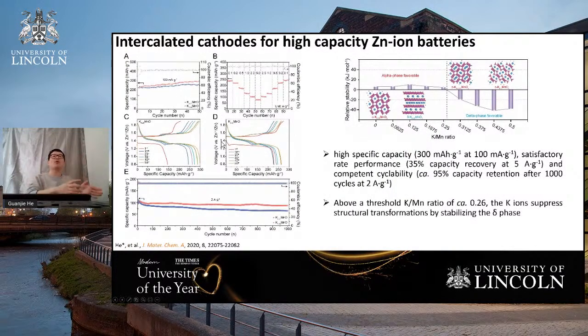Due to more potassium ions, they may occupy more host structures for the zinc ions, but our results show a controversial result. We showed that potassium 0.28, the higher amount, shows a better rate performance and also competent cyclability. So we try to understand this phenomenon.